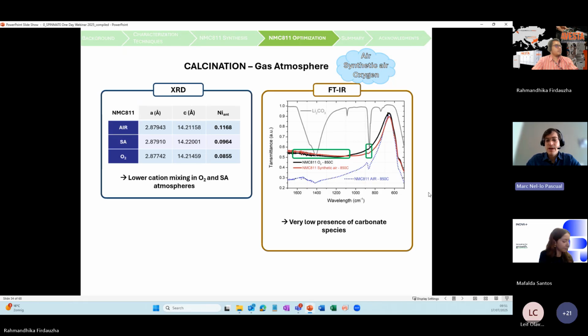In this case, if we compare the first sample, the dotted blue one, with the other ones, the synthetic air in red, and the black one is the oxygen, we see that the amount of carbonates has been significantly reduced. It's almost, we cannot see any signal coming from the absorbance of these carbonate bonds. So in the end, we assumed we have managed to reduce or almost eliminate all carbonates, so there are no impurities on those samples. However, as I mentioned, we are far from the good electrochemical performance we're expecting for this kind of NMC811, and to address this, we assessed the composition or the stoichiometry of the samples.